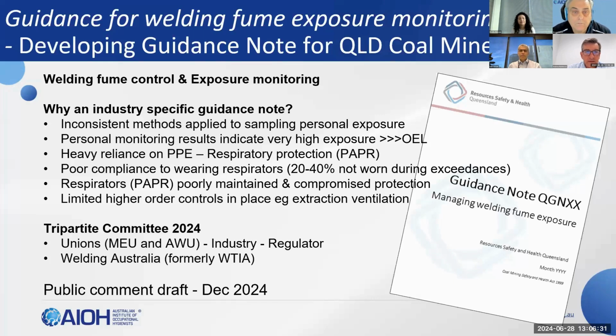What we found in that data was a lot of inconsistent methods. Sample durations for task-based range from less than a minute up to 6 to 8 hours. And the full shift stuff ranged from something like 6 hours up to 12 hours. So there's a lot of inconsistency in the way the samples were collected. The results indicated that although it was inconsistent, a lot of the results indicated exposures were much higher than the existing limit at the time, which was 5 milligrams per cubic metre.